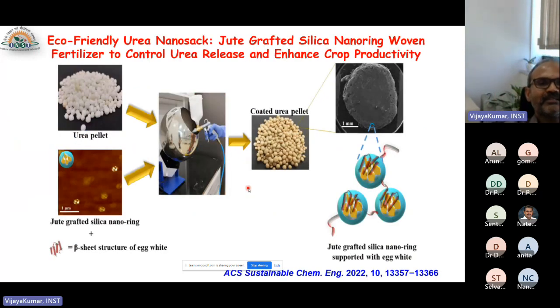Okay, so one demonstration that we have taken is we have used the cellulose waste that was discussed in the previous presentation by Divya Bharati. Here we have taken the jute waste. Jute waste has a little bit of lignin, so it itself has a little bit of hydrophobicity compared to other cellulose material. This jute has been taken and it has been grafted with silica.